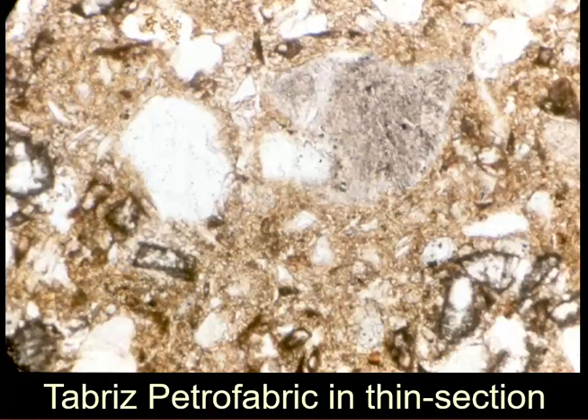The petrofabric eventually attributed to Tabriz did not look like a normal stone paste, although it contained relics of glass and inclusions of quartz. But the fabric was dominated by inclusions of felsic volcanic rock, possibly rhyolite. Hence it was hypothesized that this would have to be at a center in a location where felsic volcanic rocks dominated the local geology so much there was not a normal source of quartz.